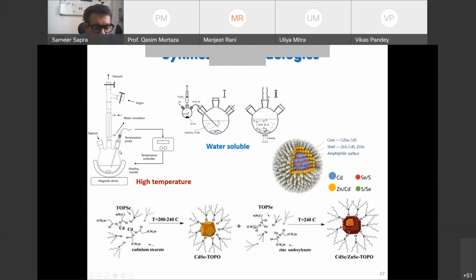What will happen instead is that cadmium and selenium precursors, which are present in this solution, get deposited on these nuclei. So essentially what you've done is something which has been known for 70, 80 years, since 1950, the LaMer and Dinegar growth models, where they say it's essential to separate nucleation and growth to have uniform colloids. If you do not separate them, when one of these particles has become this big, a new small nucleus gets formed, and you have a large polydispersity in size. So you need to separate nucleation and growth, and then you'll have very, very monodispersed particles. And that's what you want when you want to study any property as a function of size.